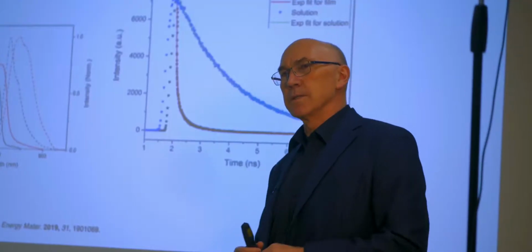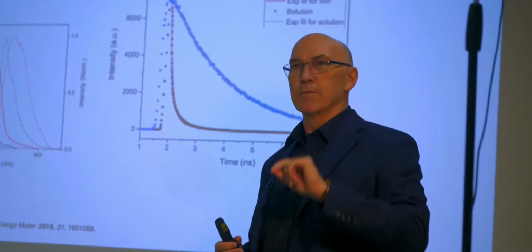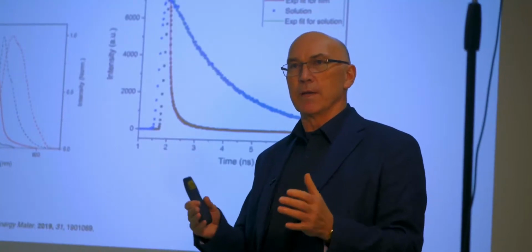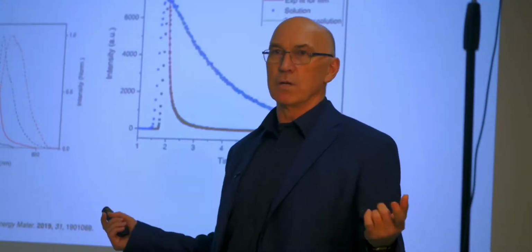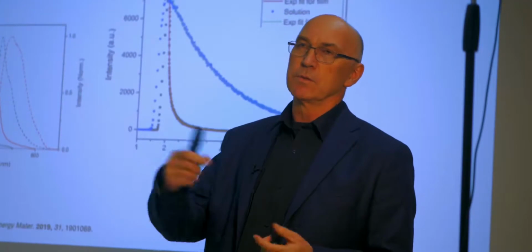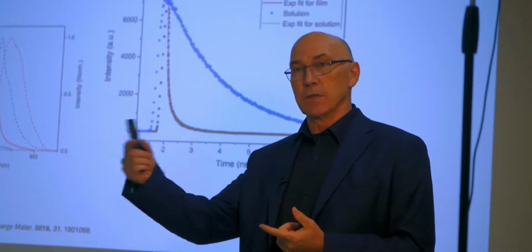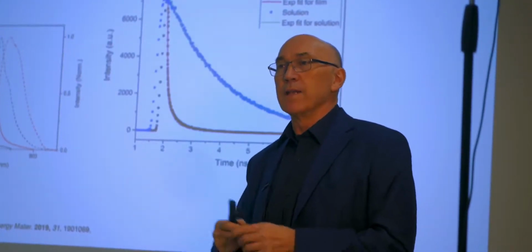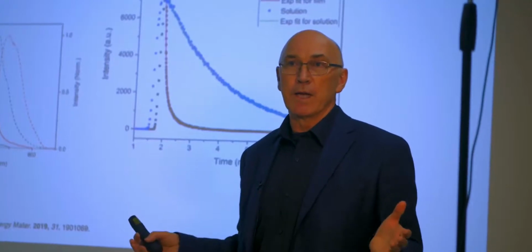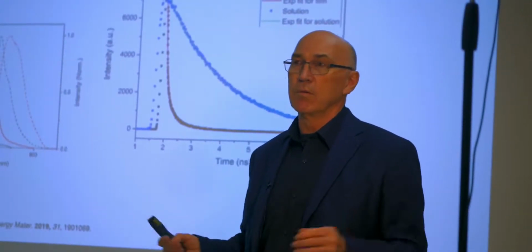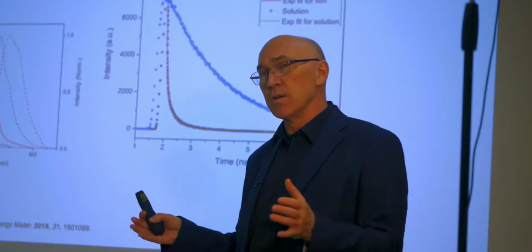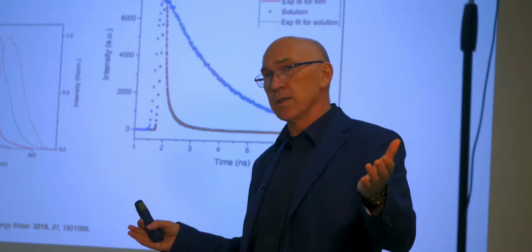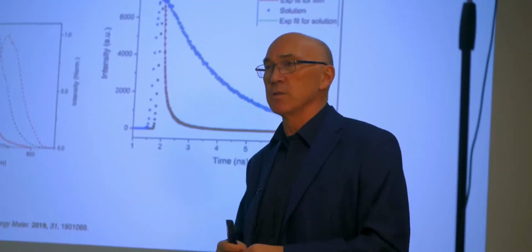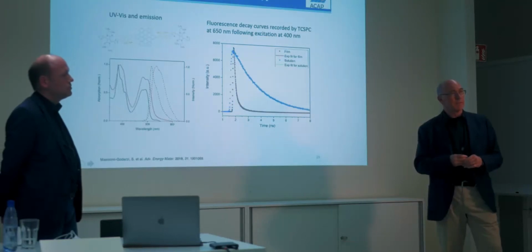It depends on what sort of stability you're talking about. One goes back to what Stefan just asked. A lot of the degradation is the fact you get moisture and oxygen coming into the solar cells, and therefore you get those secondary reactions. And therefore that's encapsulation, and we encapsulate normal solar cells, so that's not that different. We already encapsulate the OLEDs, and so we just need a slightly better encapsulant or a more robust system.